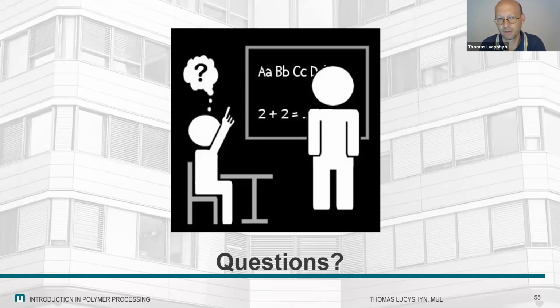And if you are recycling materials, each processing step they run through, they're damaged by a certain amount. So we cannot do this indefinitely, although it sounds very promising. You have thermoplastics, you can always remelt and reshape them, but this is limited by the damage you do to the material in every processing step. There will be some damage. In the first process step, maybe it doesn't make any difference, because those additives are consumed in this step. But in the next step, that's where the problem starts.